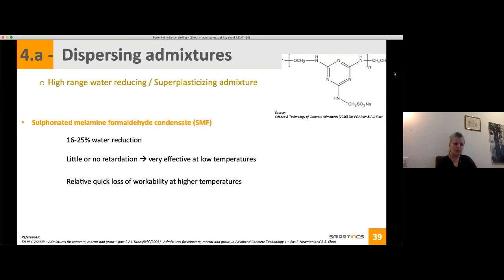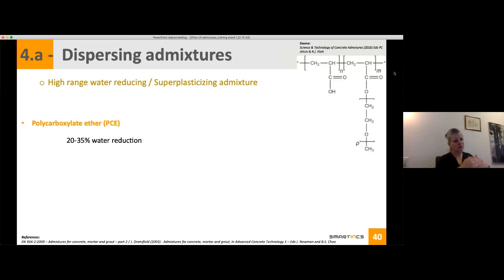If you use this type of admixture, consider that they will have a very quick loss of workability at high temperature. So depending on which application you target, is it low temperature or high temperature, this can also be a point for which admixture you need to use. The melamines are also less and less used, and that comes, and you can also see it in the name, formaldehyde. This is not so good for the health. So even if it's in really small amounts, it tends to be used less and less. And this comes also at the same time with the development of the polycarboxylate ether, the PCE.